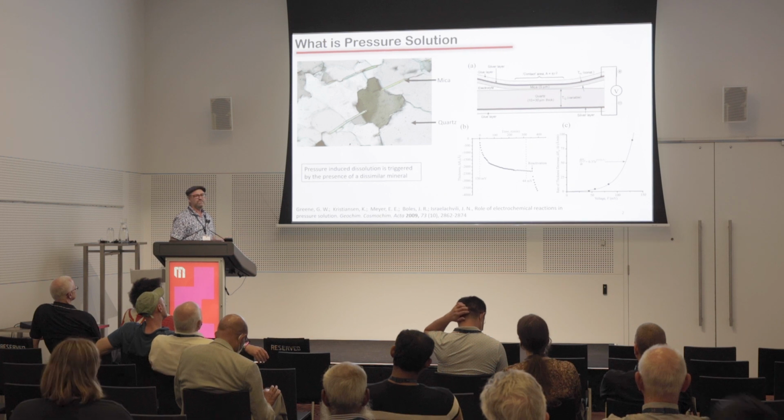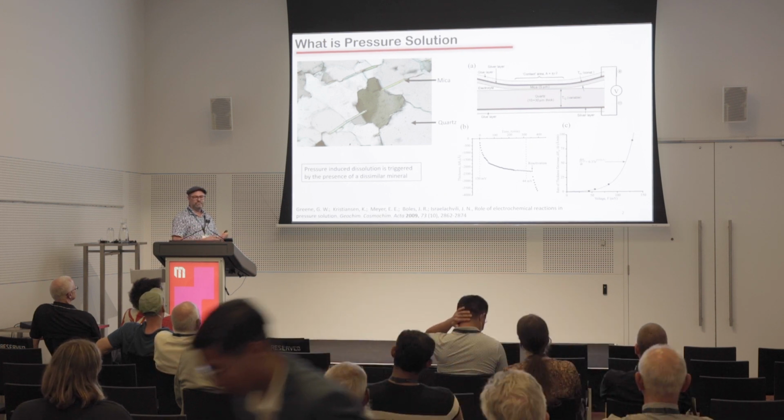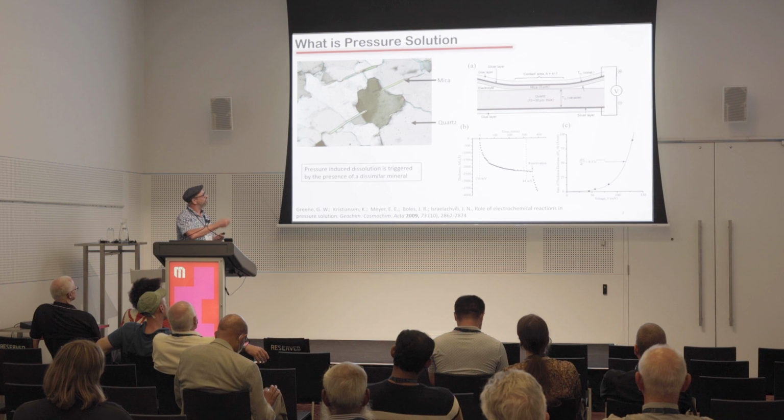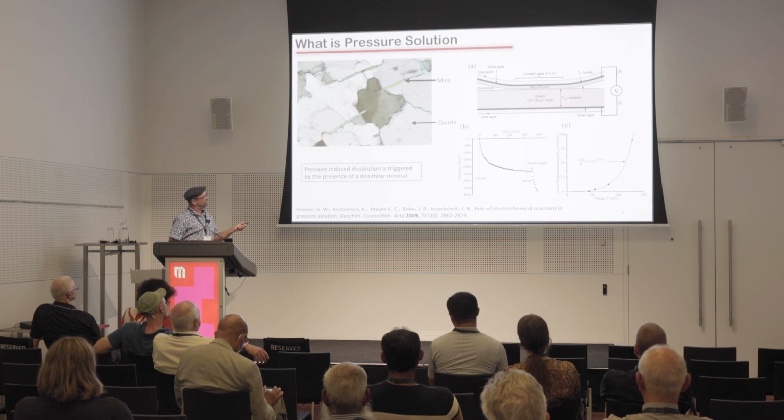And these early experiments were run using a technique called a surface forces apparatus. Essentially what you do is you have two surfaces with these semi-reflective mirrors. This creates an interferometer, and we use essentially a type of white light interferometry which allows us to monitor in real time the dissolution of this quartz with a resolution of around an angstrom, so essentially on the atomic scale.